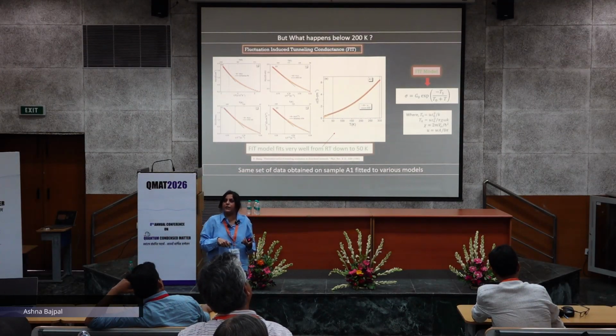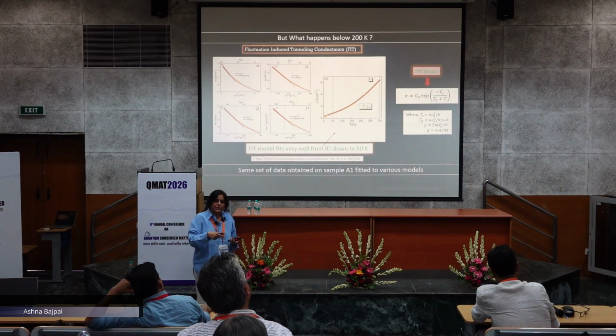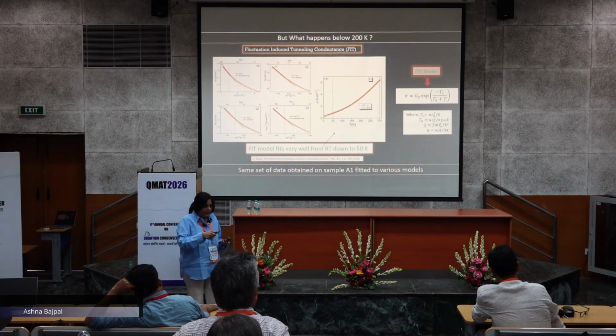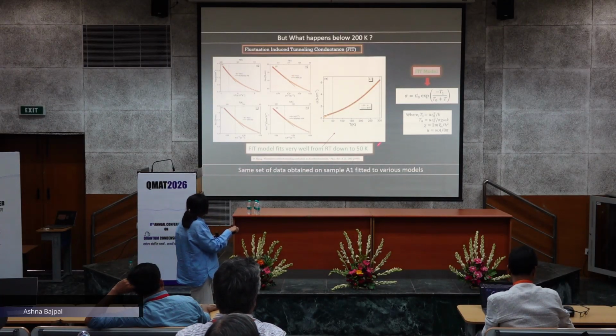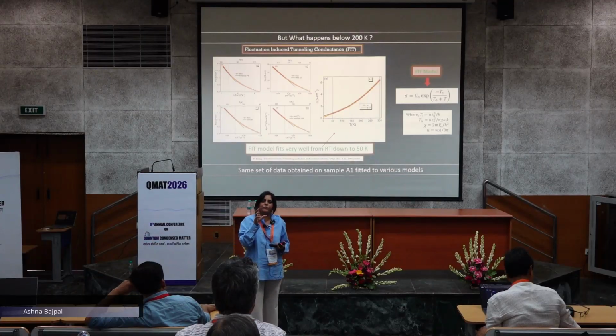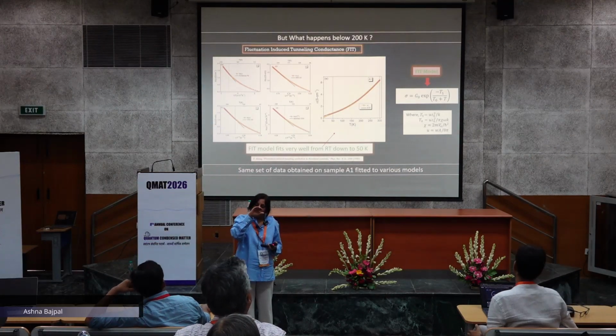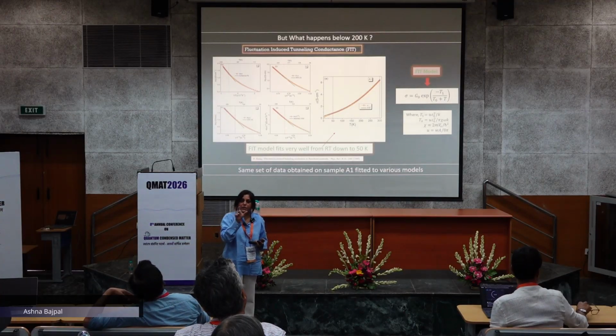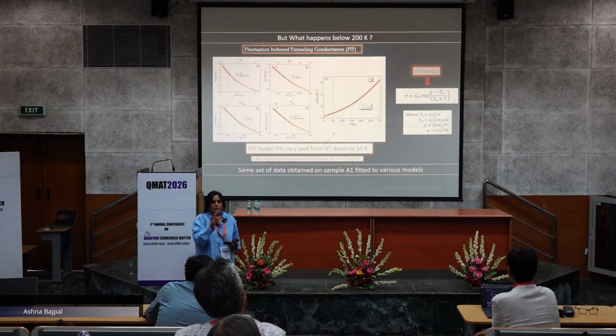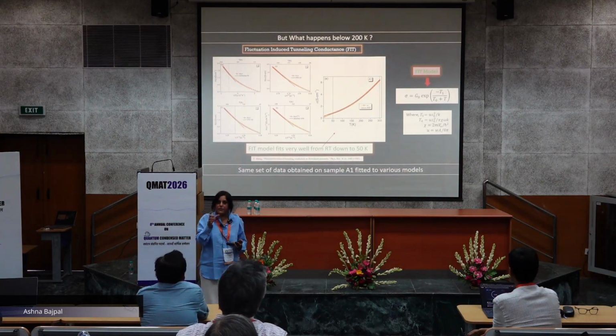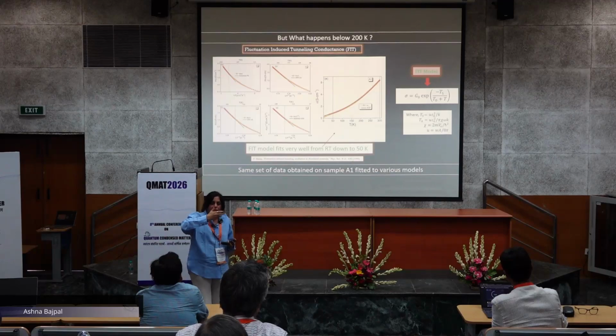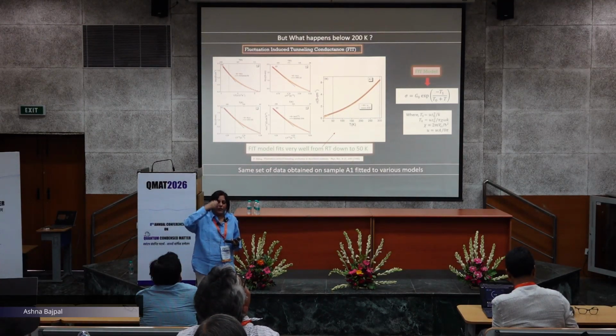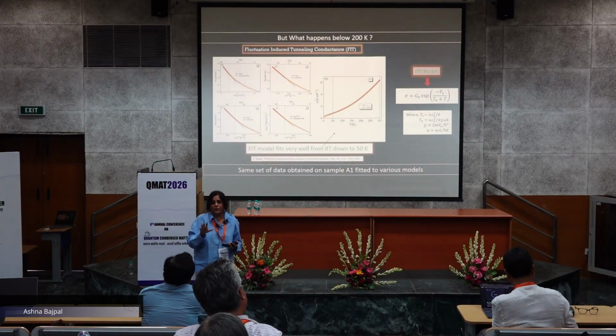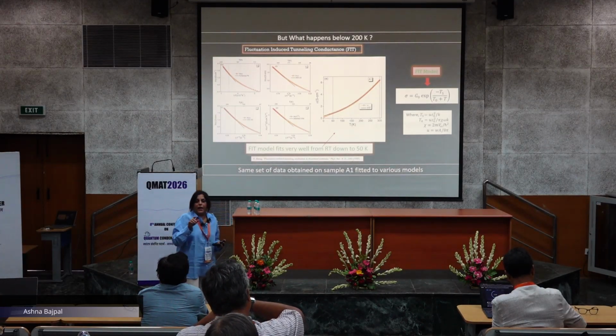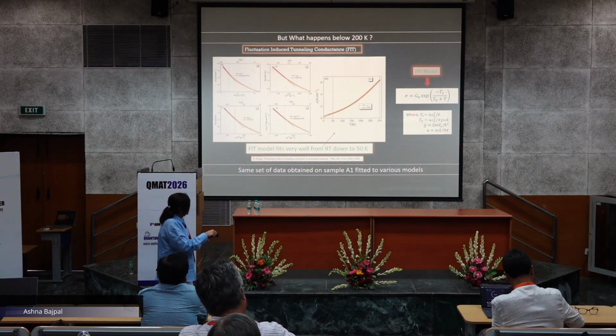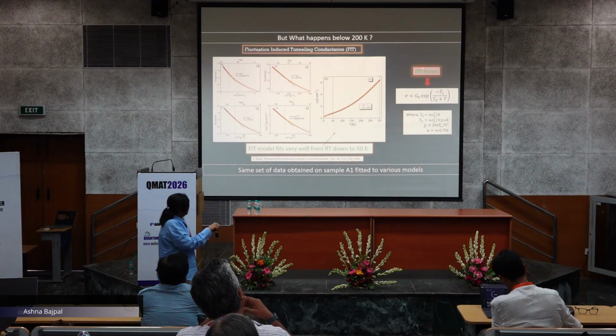This is called fluctuation induced tunneling conductance. Here thermal fluctuations basically modulate the barrier height. It is a lesser known model by Ping Sheng, way back in 1980, meant for mesoscopic conducting grains with insulating surface layer. So you have tunneling, and when your size is in the mesoscopic range, this is basically an RC network. That is how the size comes into the picture, and a single fluctuating tunnel junction can be good enough for randomly fluctuating tunnel junctions. That was the gist of Ping Sheng's paper. Through all the simplifications, this form of conductivity is expected from this model.